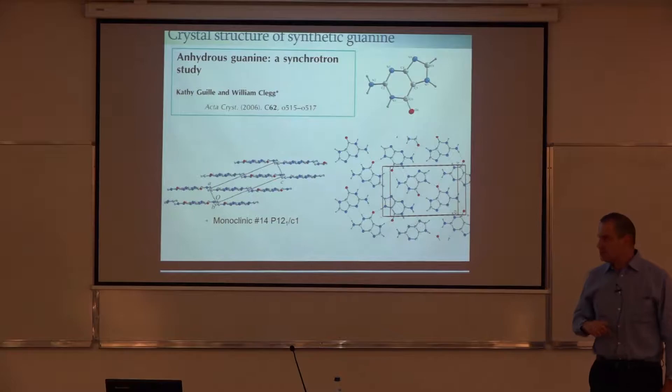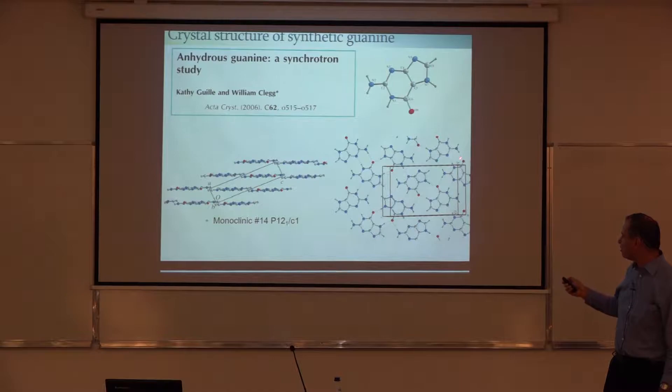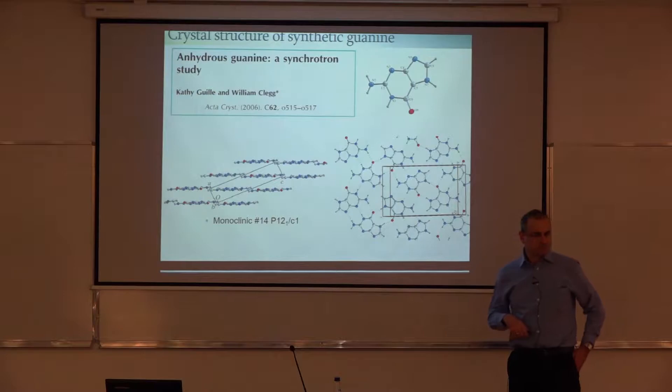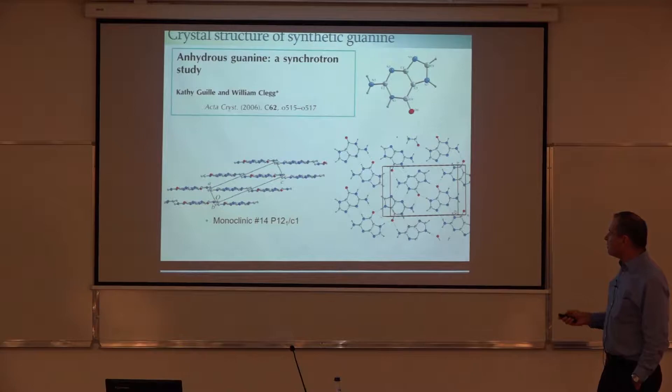It's like graphite or boron nitride in the sense that you have stacking of perfect planes. The difference is that each sheet here is actually a hydrogen-bonded network rather than a perfect covalent or ionic layer, so you can still identify each individual guanine molecule. You can see it repeating again and again in the plane, interconnected by multiple occurrences of hydrogen bonds. The question is whether these different layers match or are they twisted — and that is actually a major point of what's coming.